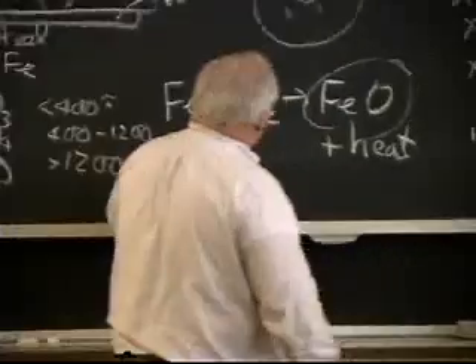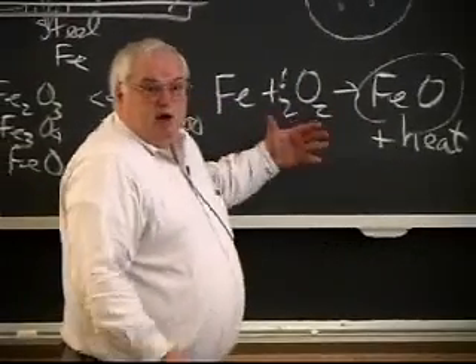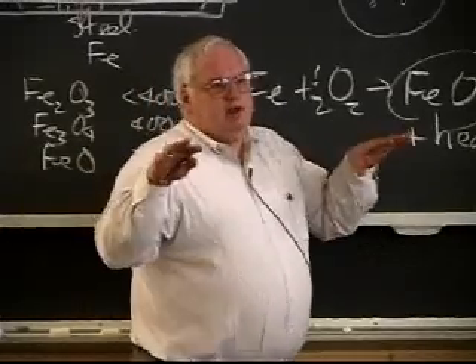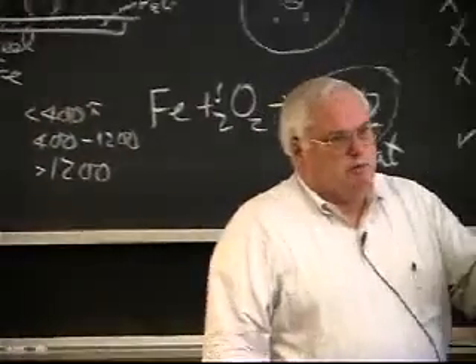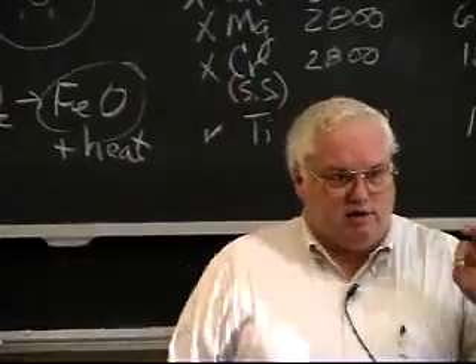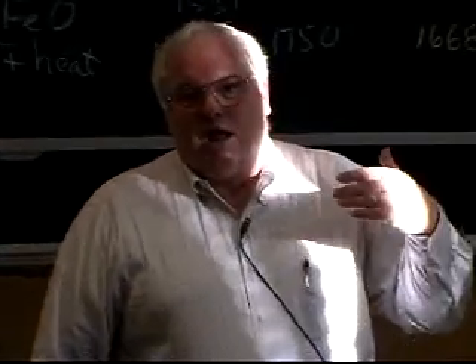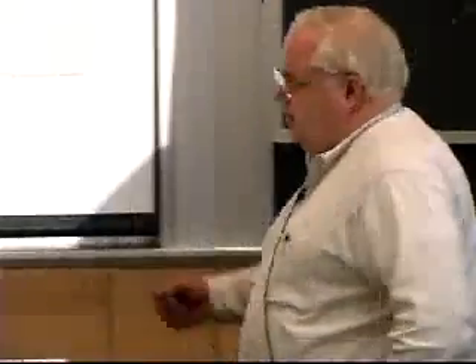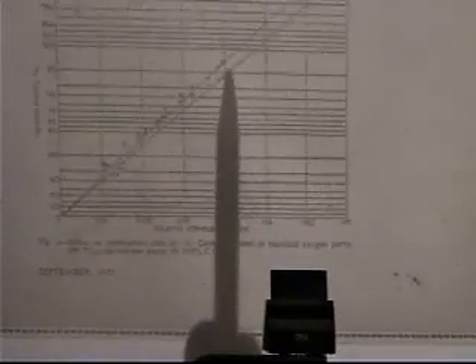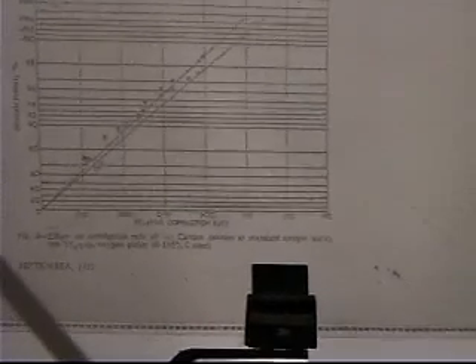And you find the speed at which you can burn goes down as your oxygen purity goes down, because in fact now I have excess nitrogen around. I've now replaced something that forms a boundary layer. It's a thinner boundary layer because it's only a partial boundary layer. I have less nitrogen than if it was air. But even a 5% impurity gas, inert gas in my system, so if I go from 99% down to 96%, I'll get about a 1/3 drop in the speed that I can cut with. So you have to use high purity oxygen.